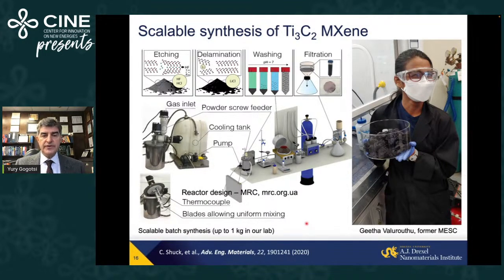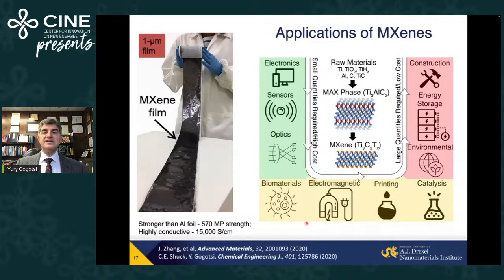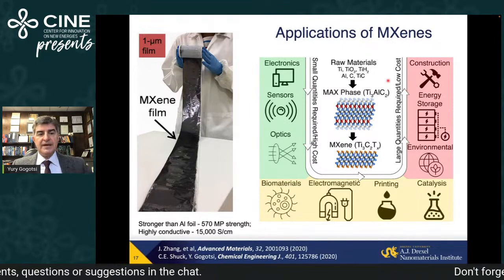If we can produce 2D material in a lab, and within the next few days we delaminate it completely into single layer flakes or few layer flakes in solution, that means that we can really use it for practical applications, not only for small electronics, sensors, optics, but also for printed devices, for catalysis, water desalination, filtration, purification membranes, energy storage. And there are already first papers even appearing, like for graphene, on introduction of MXene to cement, which actually should behave better because of hydrophilicity. Even so, I don't think it's really application justified now.